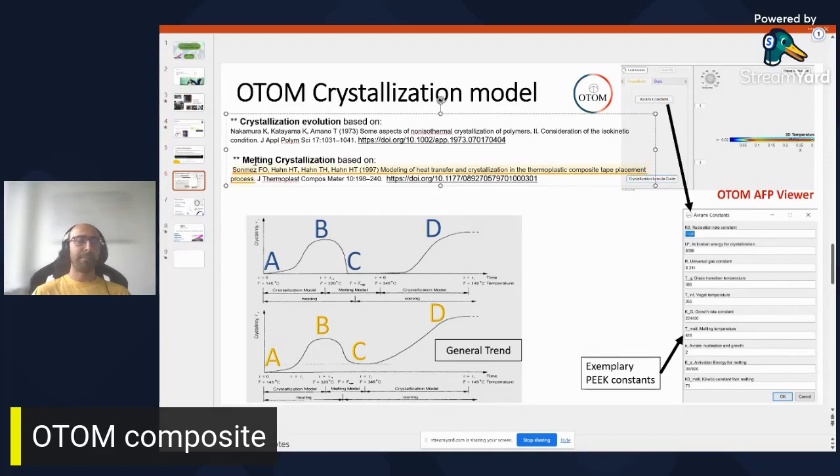And we have melting of the crystallization between B to C. Here you see B to C. Sometimes the crystallization will be melted completely, like here on the top side of this figure, or the crystallization could be partially melted, like B to C here. And it all depends on the temperature and also the time required for this phenomenon to happen.